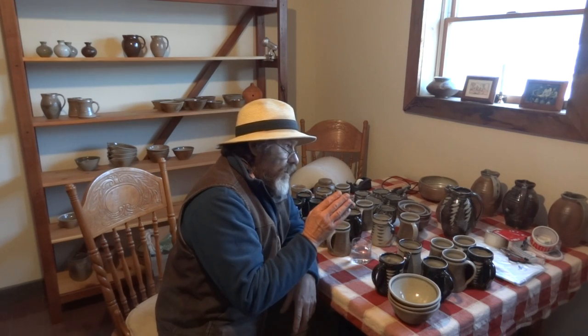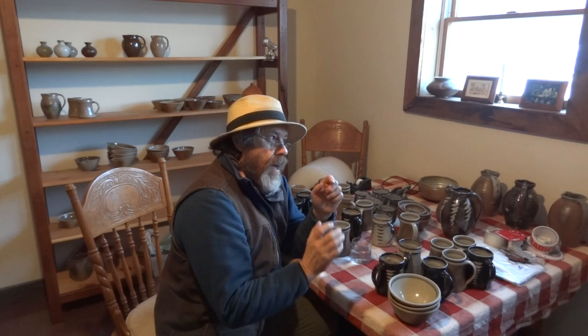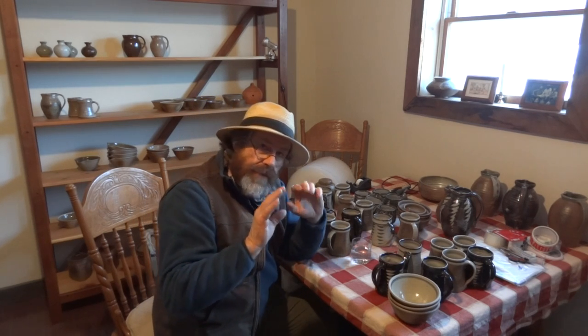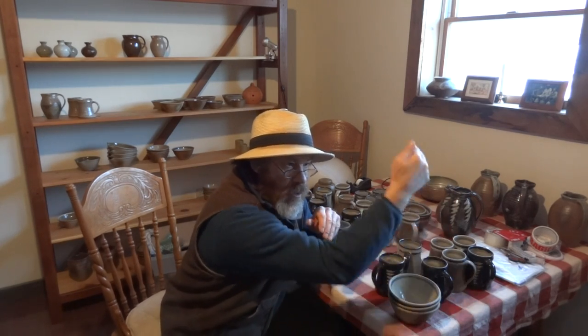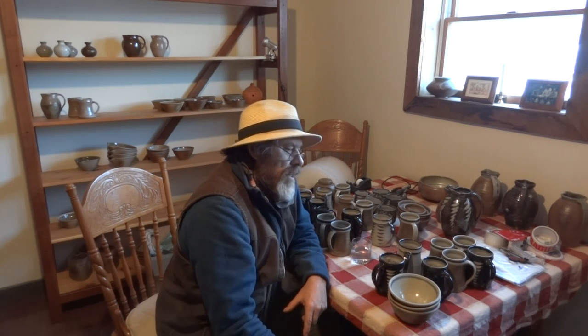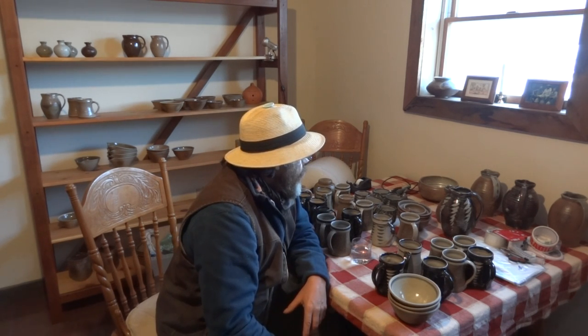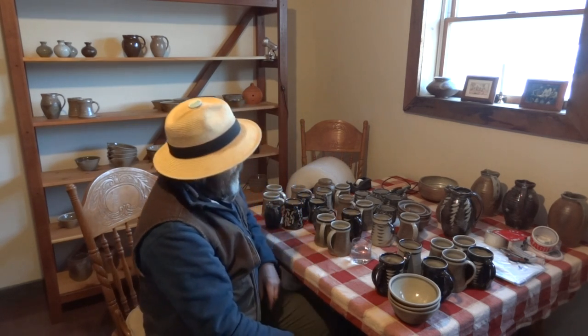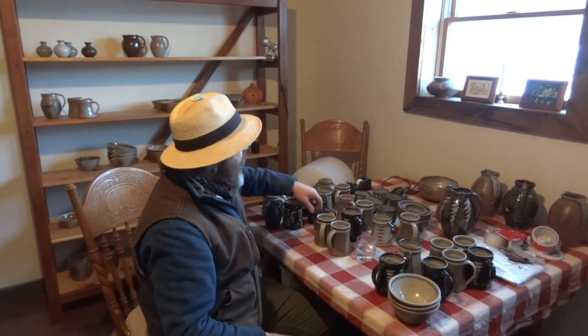And I also discovered that where my chimney flue is, a crack had opened up along the side. So what happened was those gases in the kiln that should have been circulating, being a downdraft kiln, were taking a shortcut, you see? We're taking a shortcut and going in that crack and out the chimney. So the bottom part of the kiln wasn't getting the reduction that it needed. Again, contributing to the overfiring. Anyway, I just thought I'd bring you up to speed on that.